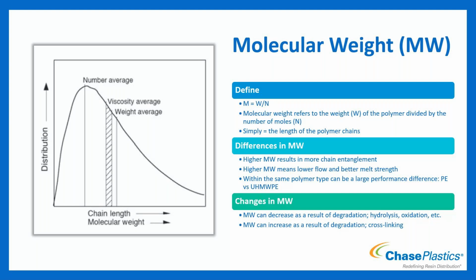It's going through hydrolysis. So there's moisture within the material when you run it, and it's breaking up the chains, making them shorter, making the molecular weight lower, or it's oxidizing. And so you're going to see a decrease in molecular weight for that. Or in some cases, certain degradation will result in the material starting to cross-link. And so cross-linking then is going to increase our molecular weight. So if we suspect that there's degradation of some sort, we can look to the molecular weight and do some testing on that to see if it gives us any idea of, yes, in fact, we did lower it or increase it and what that might mean to us.